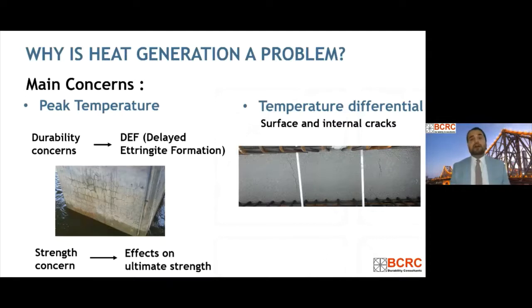The other concern is the temperature differential. When the concrete core is too hot, the temperature at the surface is cooler compared to the inner core, because the heat is dissipating from the surface. So you always get a temperature gradient, right? And whenever this temperature gradient exceeds a certain limit, there is a risk of surface and internal cracking, right? So that is why heat generation is the main problem for concrete, right?